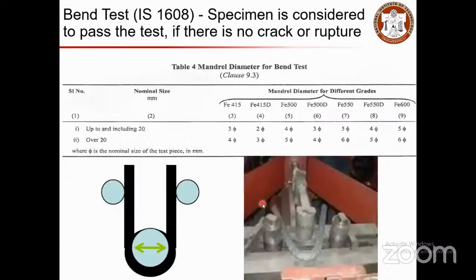So how do you do the bend test? IS 1608 gives you the specifications to do the bend test. When you do a bend test, the specimen is considered to pass if there is no crack or rupture. So you have a mandrel diameter like this. You keep your rebar going through that, and then you bend it to 135 degrees. The mandrel diameter should not be too large. You have to keep a relationship between your rebar diameter and the mandrel diameter, which will induce the stress on the surface.